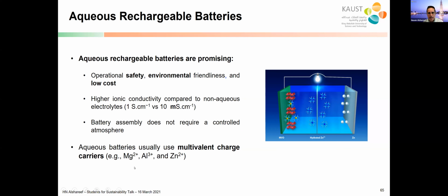Another approach people are taking is aqueous rechargeable batteries. Aqueous batteries are promising. They use a liquid water-based electrolyte instead of an organic electrolyte. They are environmentally friendly and they are safe because you don't have this fire issue. Also the ionic conductivity is higher than in an organic electrolyte. And when you assemble the battery, if your electrolyte is water-based, you don't need special glove boxes and special rooms to avoid oxygen. So this makes manufacturing easy. And a lot of these batteries can use multivalent ions, which can increase your charge storage density. But of course, they have issues. You can actually have water splitting, and so there's a limitation on the voltage you can use.